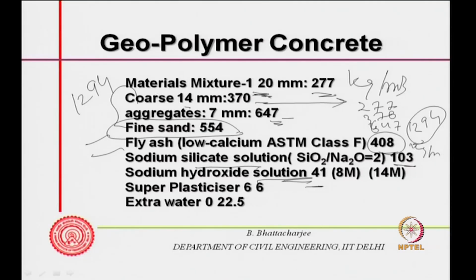Actually, the concentration is pretty high, you know, it is rich. For example, this is 8 molar concentration, this is 14 molar concentration. So, high concentration of sodium silicate solution, sodium hydroxide solution. Then use a superplasticizer to disperse the system, and you might add extra water, 22.5 kg per meter cube. So, this will have some water in the system itself plus this water.